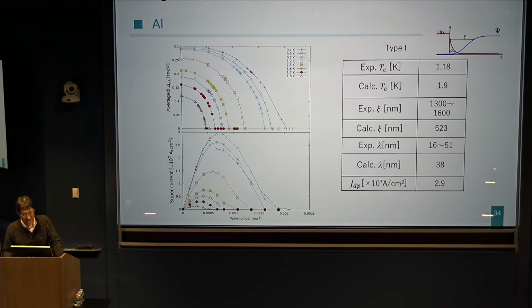And this is the results of aluminum. The calculation of aluminum is a bit difficult because Tc is a bit low, so the energy scale is very small. In our calculation, the transition temperature is a bit overestimated, and Xi is underestimated by a factor of 2. But the agreement between theory and experiment is good for lambda, the magnetic penetration depth.